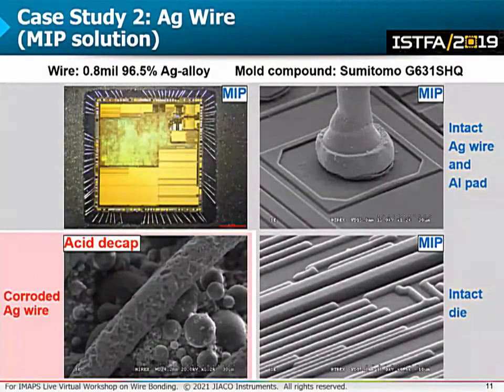This is an MIP solution to decapsulation of packages which contain silver wires. Namely, we found that the mentioned drawbacks can be overcome by using microwave induced plasma which comprises hydrogen. As an example, here we show MIP decapsulation of a package with specified silver wire and mold compound type. After MIP decapsulation, silver wires, silver ball bonds, aluminum bond pads, and also the passivation layer on the die have all been cleanly exposed without artifacts. In comparison, on the image on the left, you can see the same sample after acid decapsulation, which shows severe corrosion damage.